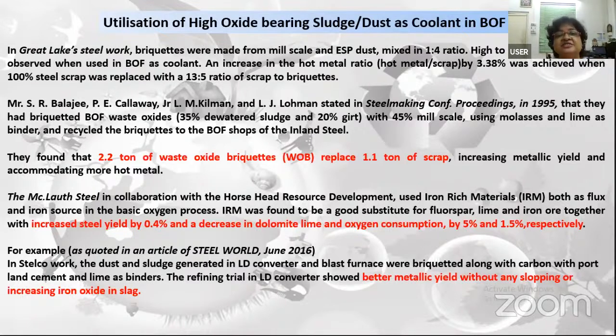Lohman stated in the steelmaking conference proceedings in 1995 that they have briquetted BOF waste oxide with 35% dewatered sludge and 20% girt, with 45% mill scale, using molasses and lime as binder, and recycled the briquette to the BOF shops of Inland Steel, and they have been successful. They found that 2.2 ton of waste oxide briquette replaces 1.1 ton of scrap, increasing metallic yield and accommodating more hot metal. This is the competitive advantage that the company is going to gain.